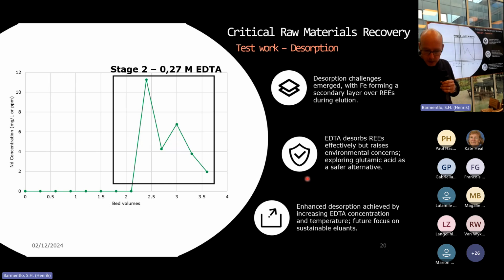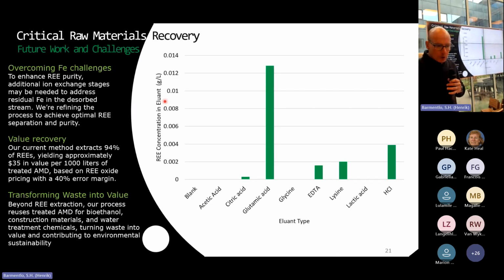This was about the desorption challenges again, and what we were seeing is that at different concentrations it comes out a bit later. So what are our future works and challenges? The one is overcoming the iron. To enhance this rare earth purity, we need additional ion exchange steps. We still have this residual iron problem, and we're refining this process to try and achieve optimal rare earth separation and purity.